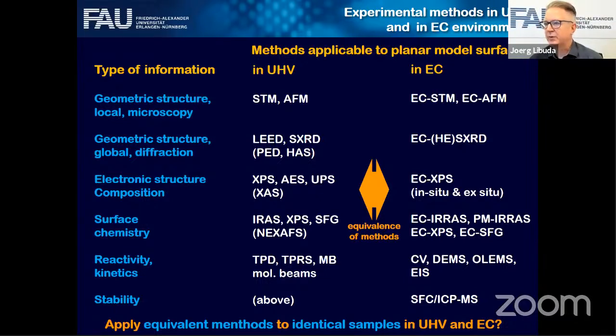Yeah, I think this is a very important question, and it's also the biggest challenge. I think the answer is it depends very much on the system that you're looking at. If you have, for instance, a very reactive, clean, noble metal platinum surface in mind, this is a big problem. On that surface, everything will adsorb, and many molecules will spontaneously decompose. Of course, you can try to deactivate the surface in a controlled way. For instance, you could put adsorbates that adsorb sufficiently strongly. An example would be CO, to protect the surface a little bit while you're doing this transfer.